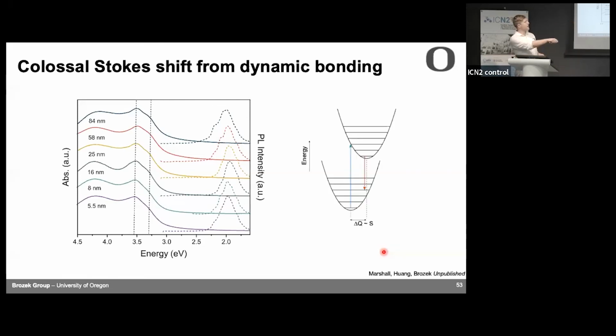And we think that this gets back to this idea of the dynamic bonding in MOFs, the really big S value, the really big Huang-Rhys parameter. You excite, and then when you relax in the excited state, the geometry is so different from that dynamic bonding that it fluoresces at a really different energy.